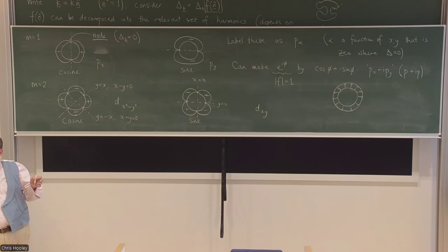We will look at that more carefully when we do where these things come from. There's a generalized version of the gap equation where the interaction depends on k. And one can show that for the right k-dependent interactions, which includes some repulsive cases, it's actually optimal to pick d wave. But the highest TC superconductors we know are the hydrides. And to the best of our knowledge, the hydrides are S wave.